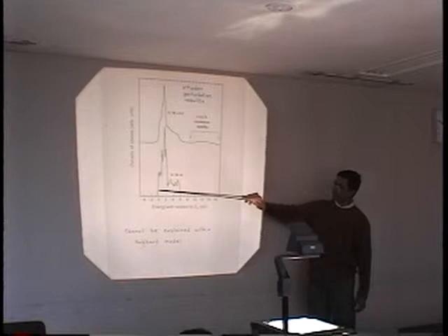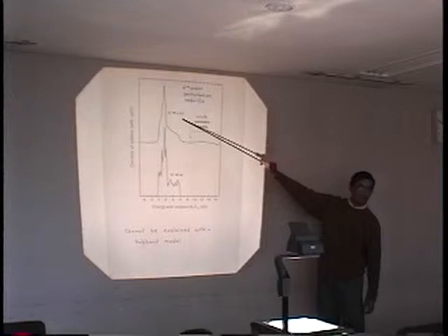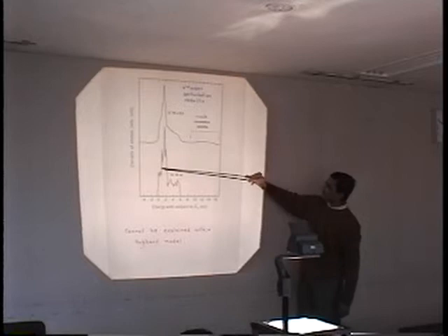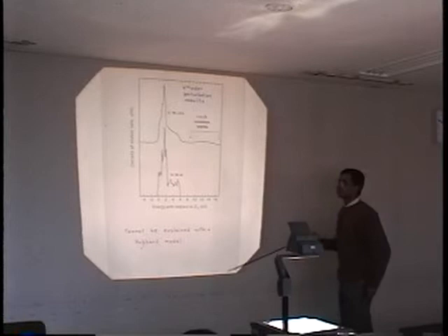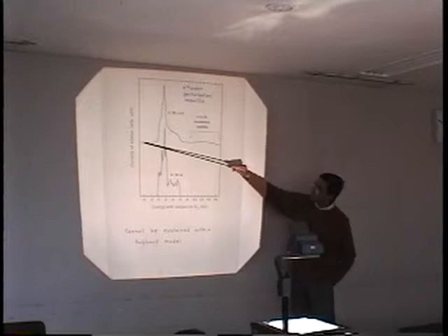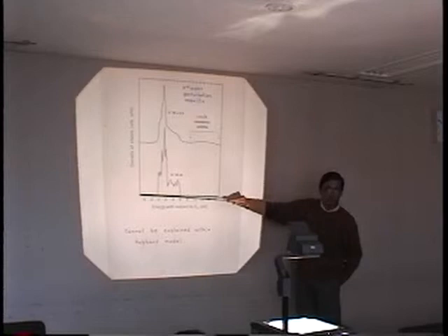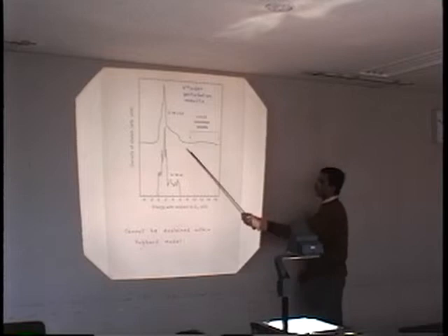Start with that one and switch on correlation in a second order sense, and so U by W is small enough to do that. You find that these sharp spectral features broaden a bit, which of course comes from the real part of the self-energy correction. But there's no satellite that you see in the occupied part. Remember, this part is the occupied spectroscopy, probed by occupied spectroscopy. There's absolutely no satellite, but in the unoccupied part, which is this part of the energy, you start to see